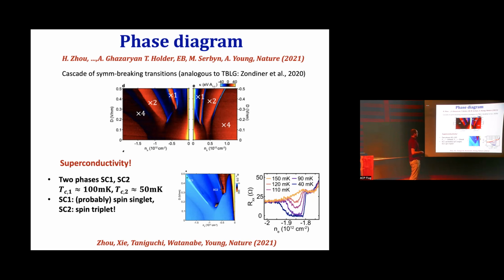Okay, so as condensed matter physicists, what we'd like to know is what kind of superconductivity happens here. There's already a hint here. I've shown you before these different phase diagrams of different correlated materials. Unconventional superconductivity tends to appear right at the boundary of some other competing phases, typically a magnetic phase. This is exactly what happens both in SC1 and SC2. They live right at the border of different phases with different broken spin and valley symmetry. So this is already a hint.